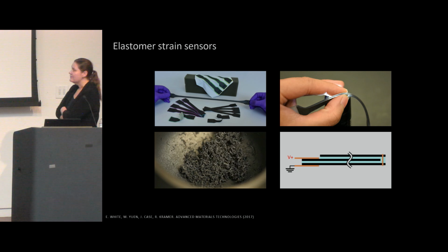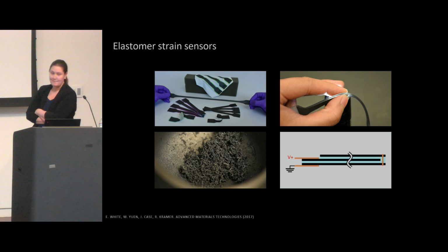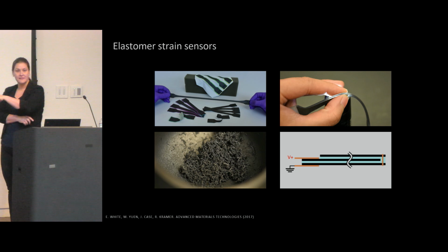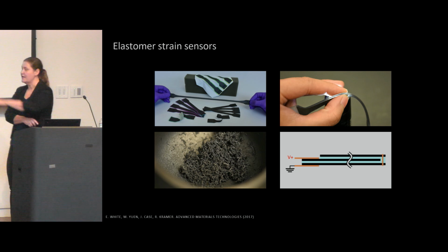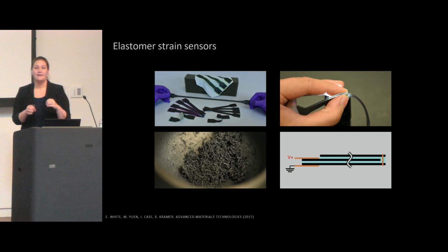We took chunks of graphite and soak them in a solvent. Then we put the solvent-soaked chunk in a really hot environment, in a hot crucible in this case, and it vaporizes the solvent. The solvent goes above its boiling temperature and starts to push the flakes of the graphite away from one another, which is what you saw in the video. So that's the exfoliation process of these graphite flakes being formed.